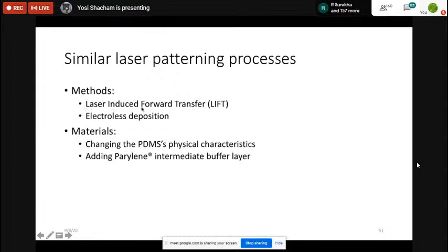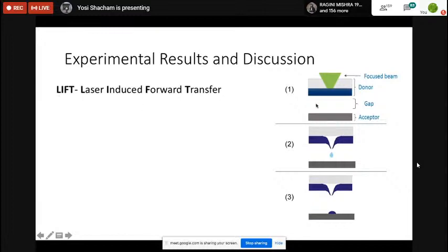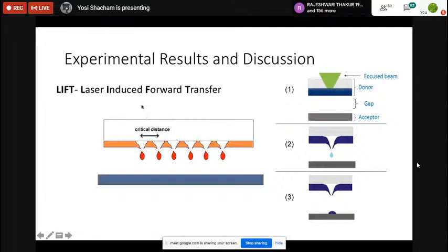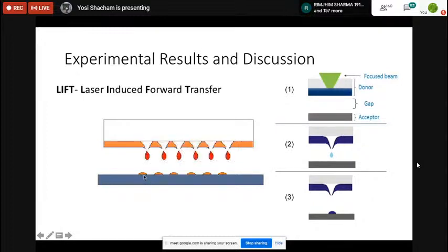So we looked at, we have a laser, and there is a technology called LIFT. And LIFT is the following. You take the glass, and on the glass you put the metal. And then you are illuminating from the back side with a laser. Because you're illuminating from here, you are generating a drop, and the drop is going down and deposited on your substrate. So you go to a different point and deposit another drop, and then deposit another drop. And then you can make an electrode. So this is called LIFT.